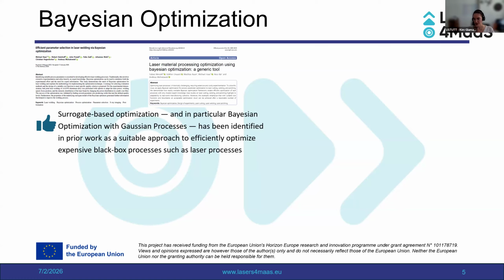Therefore, it works really well with low dimensional parameter space, so no more than 15 to 20 parameters. The less actually is the better, because the fewer parameters we want to optimize, the fewer experiments we have to do in order to get suitable results. But the really nice thing about Bayesian optimization with Gaussian processes is also that it can handle noisy data. And everyone who works with process monitoring knows how noisy data can be that we monitor.